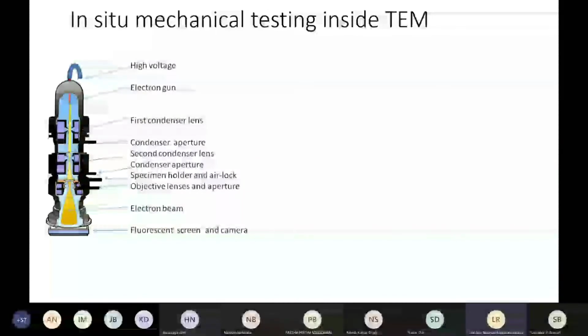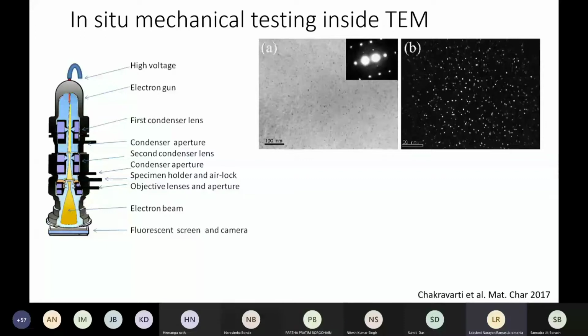We look at something called a transmission electron microscope, very popularly known as TEM. And here what you do is you apply a high voltage and you let an electron beam pass from the top from an electron gun. And then the electron beam passes through several magnetic lenses. And what these magnetic lenses do is they condense this beam and then they pass through a specimen, okay, which is placed on a holder. And finally, the specimen has to be transparent to the electron beam, and then it goes to a fluorescent screen and a camera. Now, there are two types of detectors. When you have this transmitted beam, it can collect two types of information.